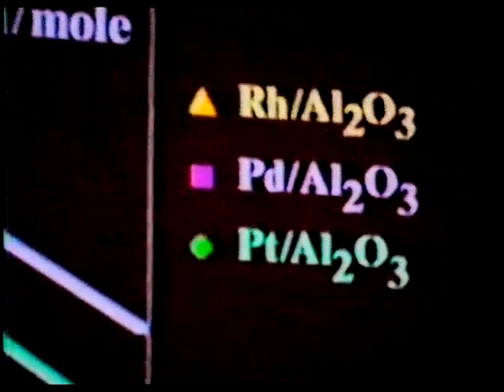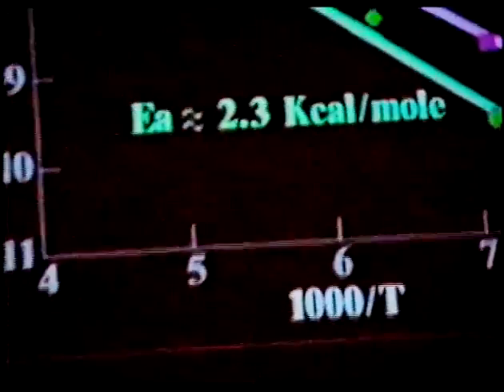platinum, as I already showed you, you can go ahead and use these strong ethylene bands to measure activation energies for the conversion. Even though you can't see the di-sigma-bonded species in some cases, you can definitely see the pi-bonded grow in. And what's shown here is that the palladium has an activation energy that's not too different from the platinum.